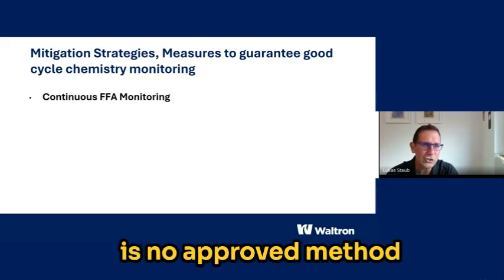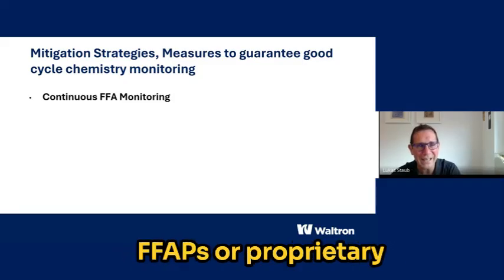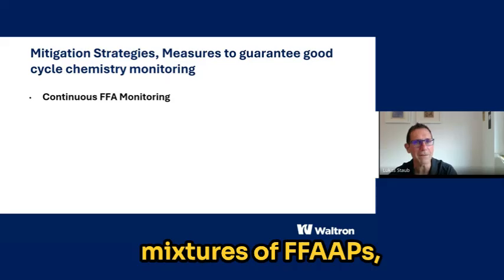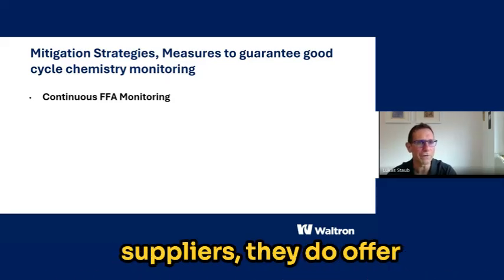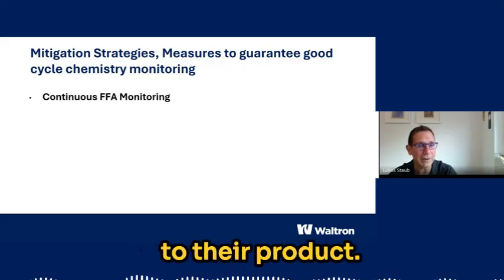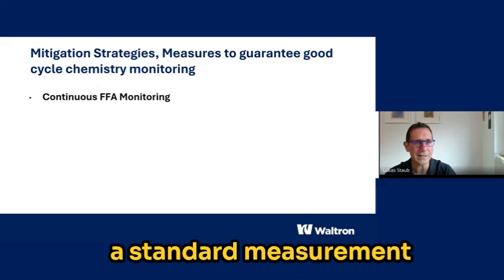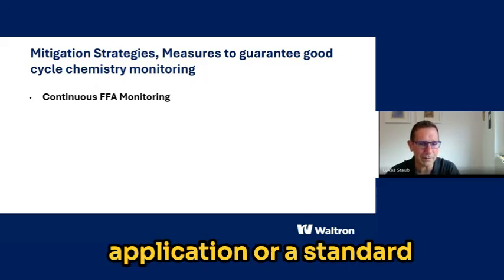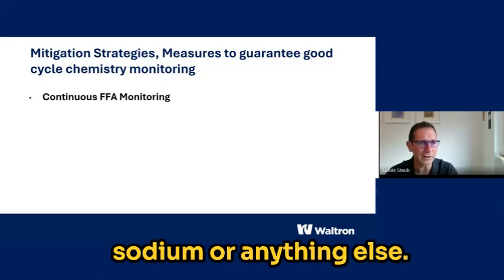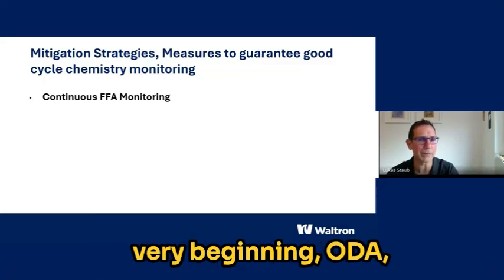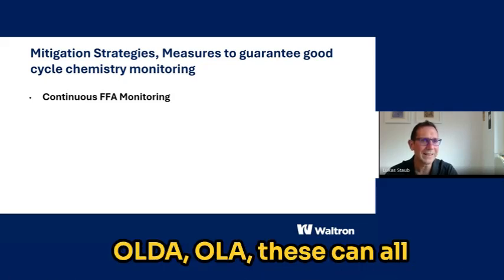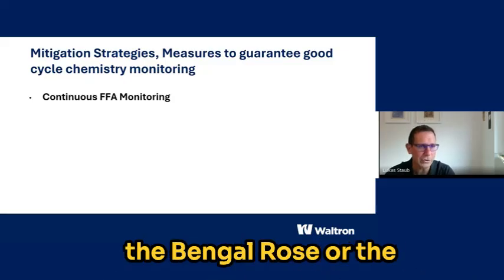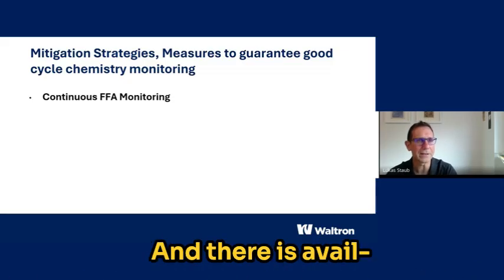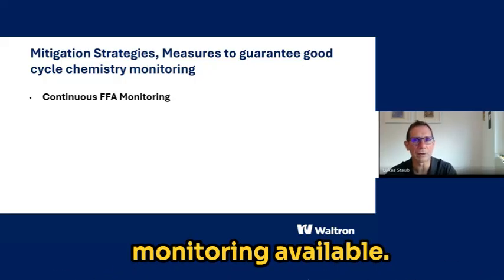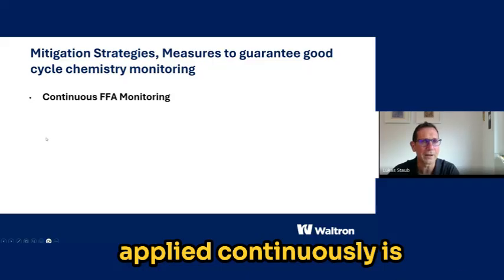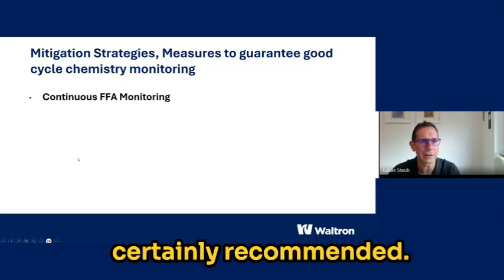Now, generally, there is no approved method available for any other FFAs or proprietary mixtures of FFAs, although some chemical suppliers do offer proprietary measuring equipment specific to their product. But it's not like when you have a standard measurement application or a standard measuring method for sodium or anything else. The FFAs, the classes that I mentioned at the very beginning, ODA, OLDA, OLA, can all be detected with either the Bengal rose or the methyl orange method. And there is online monitoring available. So continuous FFA monitoring applied continuously is certainly recommendable.